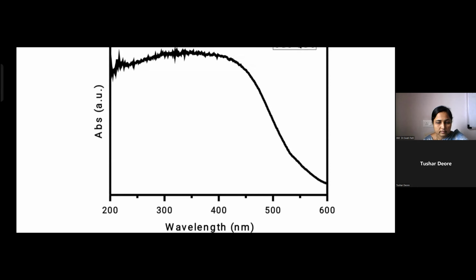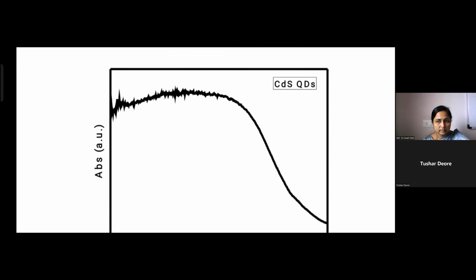But my UV spectroscopy maximum wavelength occurred at 440 nanometers, and we concluded the band gap is 2.78 electron volts by the Einstein energy equation, E is equal to hc upon lambda, where h is the Planck constant, c is the speed of light, and lambda is the wavelength we used.